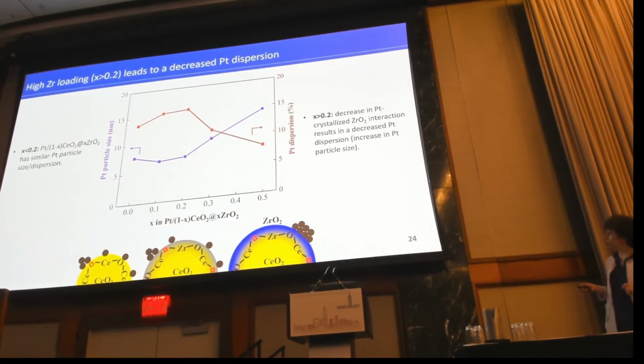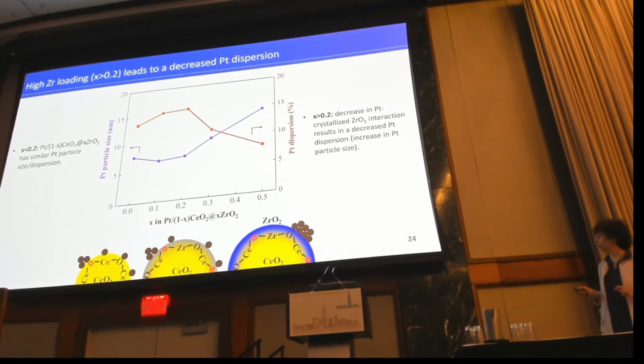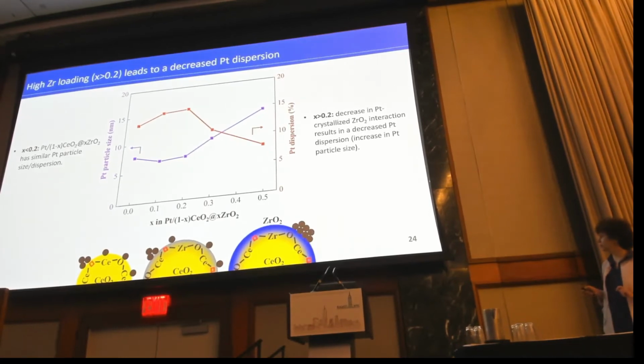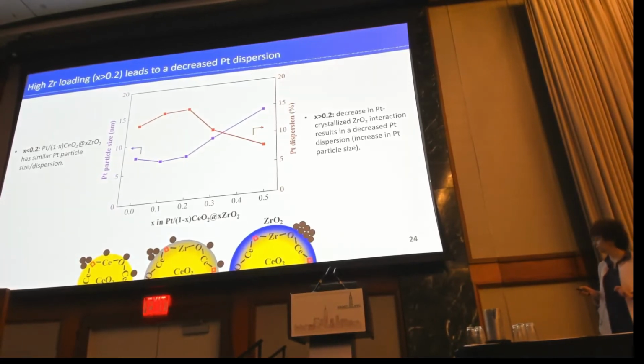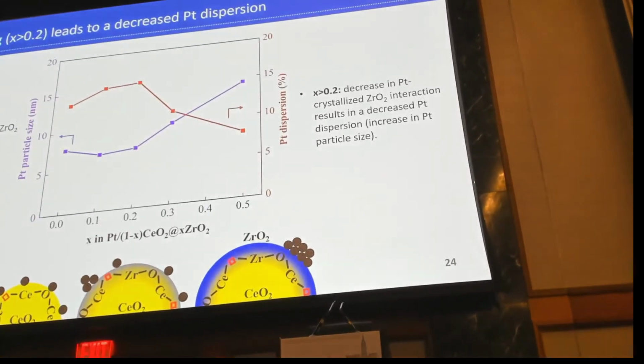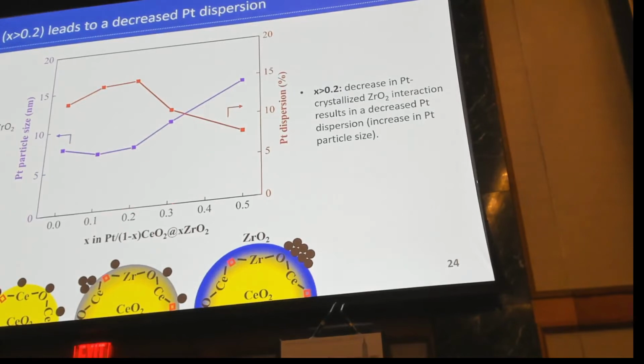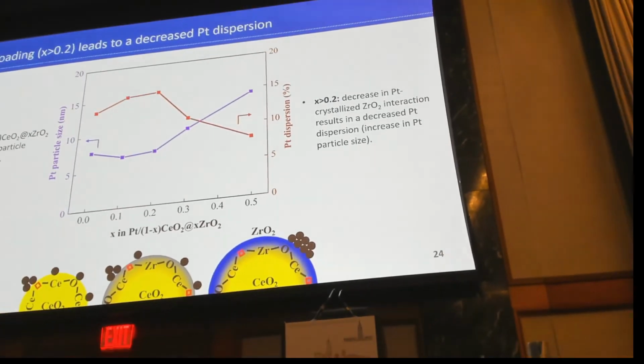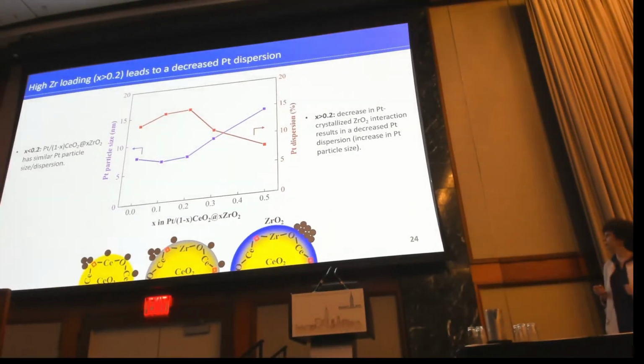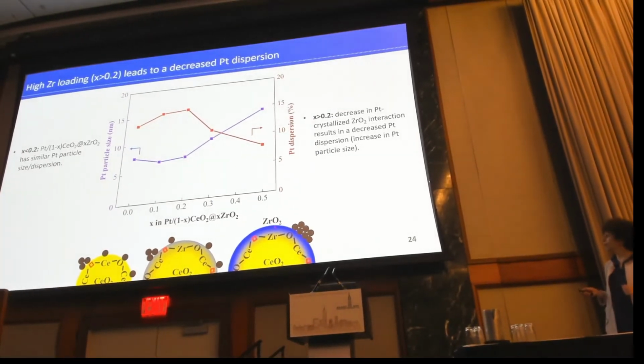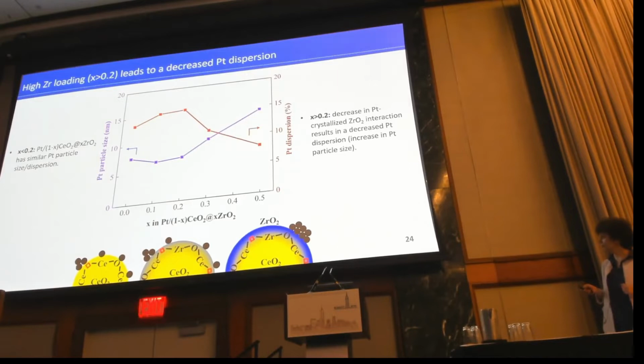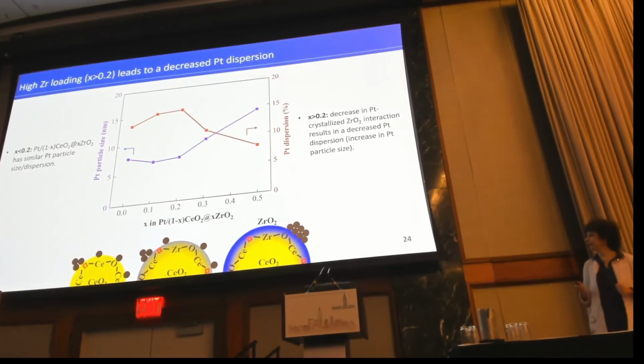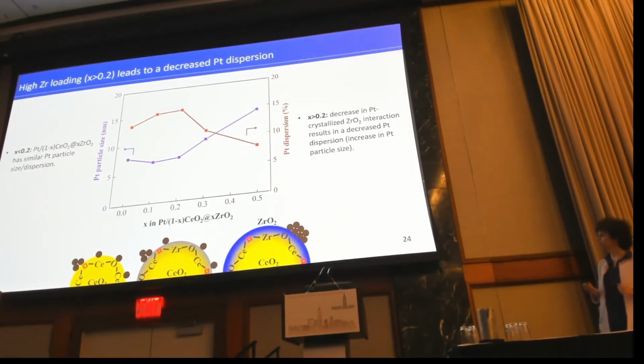We increase the zirconium content and we're able to see that the particle size increases and the platinum dispersion decreases, which is expected. So basically what we think is happening is that when we start adding more zirconium on the sample, we start forming crystallized zirconia, and then platinum forms these big platinum particles that we saw in the CO chemisorption results. But of course, we want to use another technique to verify this observation.